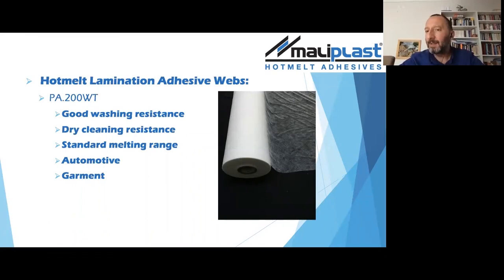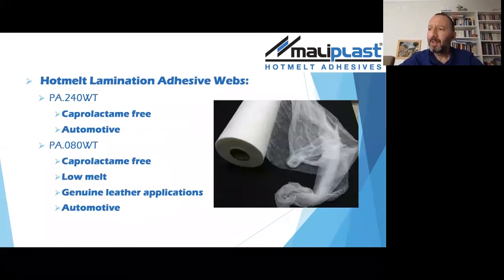On the polyamide side, the biggest advantage of polyamide is that it has good washing resistance and dry cleaning performance. The first product that I can mention is our PA200WT. It has very good emission values, which is very good for automotive applications, especially for automotive seats. It is used in some filter applications, and also in garment applications, thanks to its washing resistance. PA200WT has an average melting range at around 110, 120 degrees.